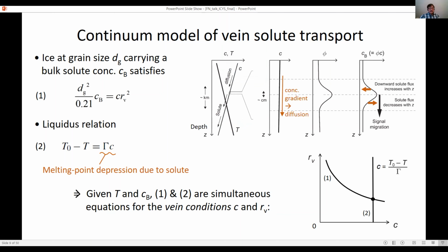It's particular to the ionic species being considered as a binary system with water. And in their theory, this liquidus relation translates, as you can see over here, the rising temperature towards the bed, especially deep in the ice column, to a decreasing, there's a minus sign here, decreasing impurity concentration of veins, which drives that downward diffusion of chemistry in the vein network. When you zoom in there, the gradient is very shallow, very slow diffusion of chemistry, but that interacts with the porosity expression of a bulk signal to move the signal. And the way it works is that on the upper side of the signal, the porosity increases with depth, and so the downward chemical flux increases with depth, and that draws down the signal.